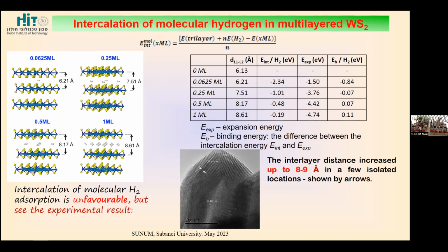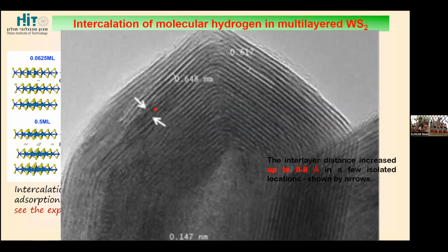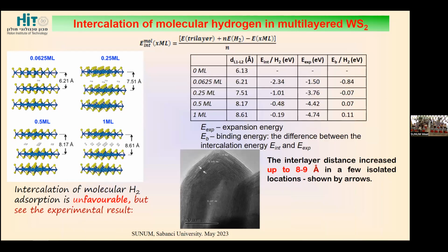This is theory, but sometimes what is forbidden in theory is allowed in the experiment, as we have a plasma process with quite a lot of energy. And when we measured our nanoparticles by, for example, TEM, then we indeed observed exactly this extended interlayer distance of about 8 angstroms as compared to 6.2, 6.5. So though theoretically quite unfavorable, this process takes part in reality. So we do have some intercalation of hydrogen, and there is a lot of space for hydrogen inside. So this can be one of the mechanisms.